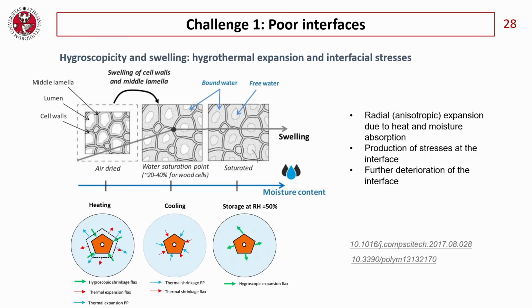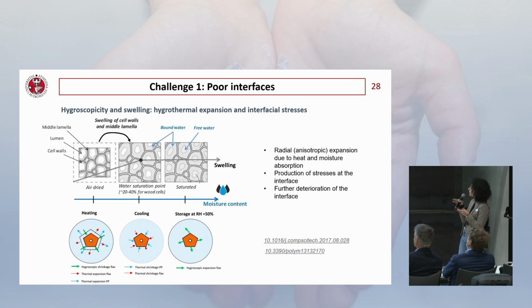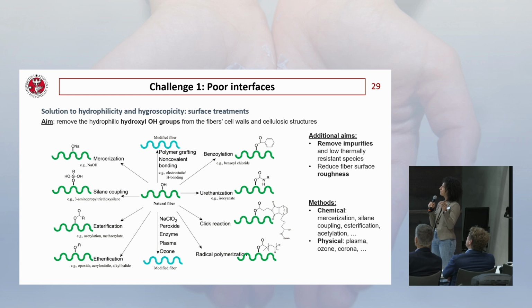This occurs both with hygroscopic matrices like polyamides, but also with non-hygroscopic matrices, because all the matrices present porosity. Moreover, the single cells, the single fibers, can swell due to their hygroscopic nature, and this, again, will be an anisotropic property. They will swell differently in the axial and in the radial direction, and this will cause a further deterioration of the interface.